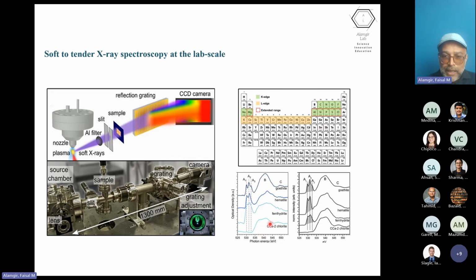So here's an instrument that is now currently commercially available. Here's a picture of the instrument itself and some schematic drawing of how it works. In this case, the X-ray is generated by irradiating a gas with a laser, and so you then generate a plasma, and without getting into the physics of all of that, you generate a broad spectrum, but on the soft X-ray inching towards the tender X-ray region, that part of the spectrum. And so that's perfect for what we need. And so we use that X-ray source then to do the kind of experiments that I've been describing previously.